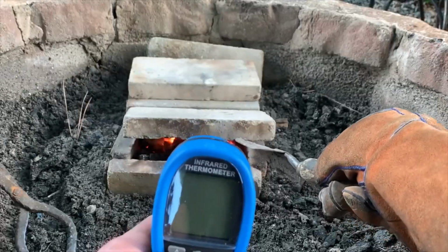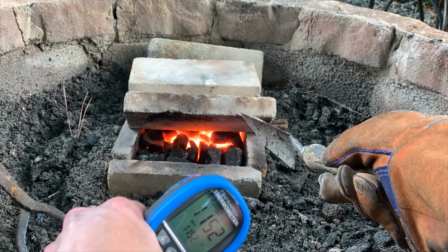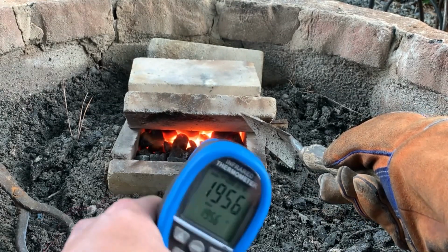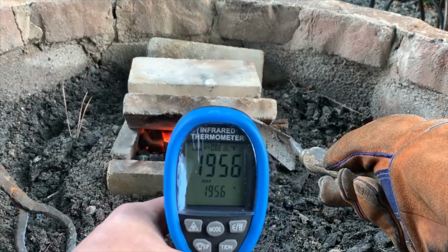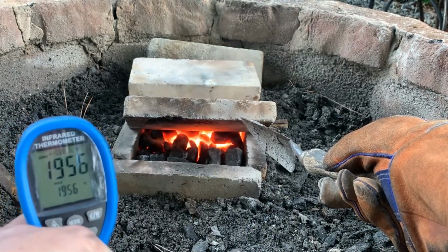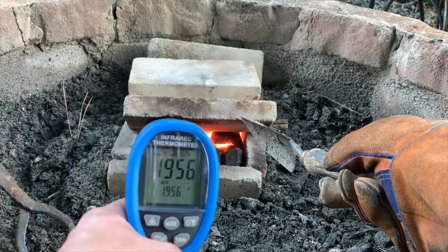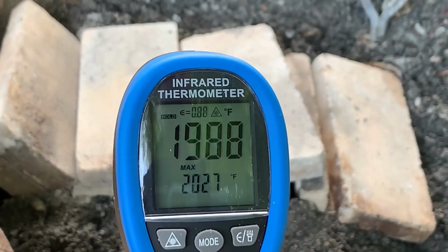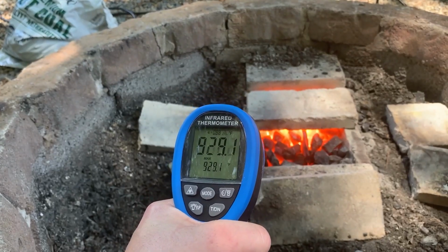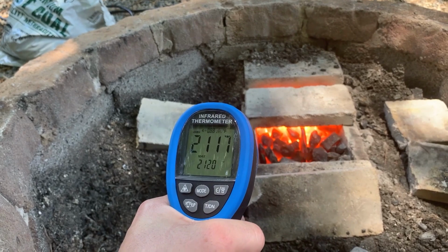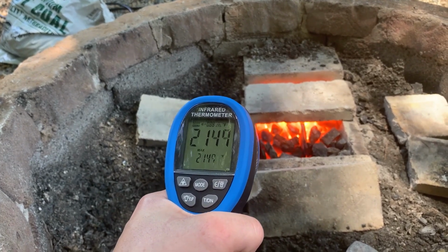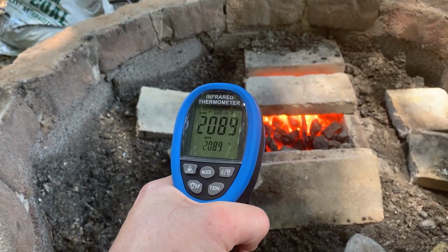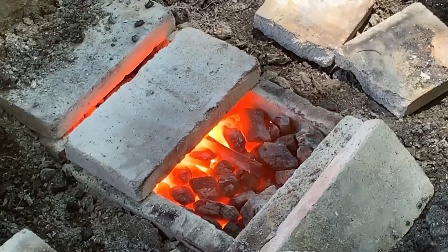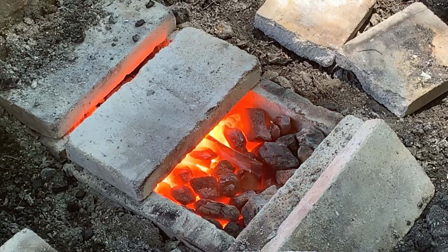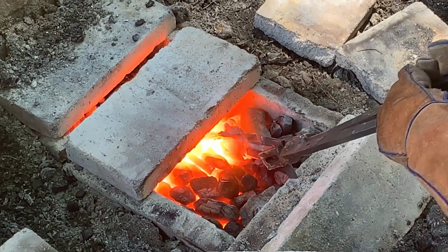So as you just saw, I began heat soaking the blade once I got around 1400, and you don't see it, but I did dig a little trough and place the blade in it, spine up, cutting edge down, once I hit 1900. That's where things got really interesting, because for the remaining duration of the heat treat, about 30 minutes that is, my oven effortlessly remained between 1900 and 2100 Fahrenheit, which is pretty much exactly the range you want for a stainless heat treat, and I was pleased to say the least.